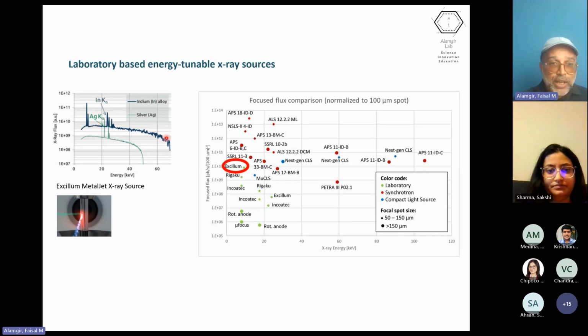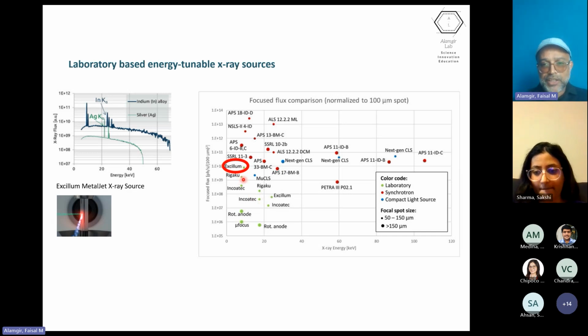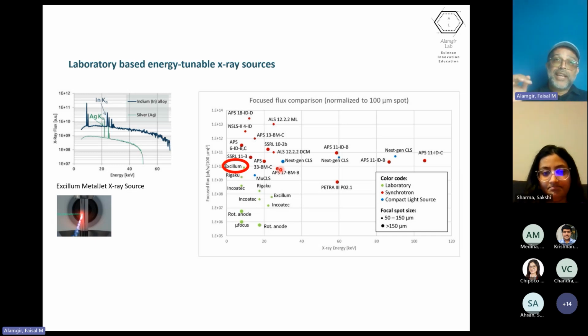So what I'm showing here is that, for example, if you use an indium target or a silver target, you see this broad spectrum of X-rays that you're generating. Normally, all of this is thrown out, and what we use are these characteristic emissions. But if we change our thinking, we can use the broad spectrum and basically avoid the characteristic emission regions in order to use a broad high intensity spectrum. So here's a table now comparing what we might possibly get to with lab-based sources in terms of intensity, sort of an apples to apples comparison with the synchrotron beamline type of capabilities. And you can see that in the best cases that we can imagine for our lab-based ones, the green dots here, we are still going to be several orders of magnitude shy of what we get at a synchrotron, but that may just be enough.